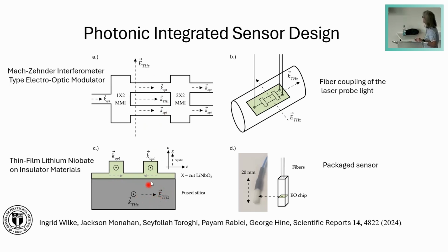These are technical details. We have X-cut lithium niobate, and the polarization of the optical mode is parallel here to the extraordinary axis of the material. Then we see here how we operate it. This is again a top view schematic of the chip. The laser light is coupled from the fibers to the device using grating couplers. And here the cylinder indicates the terahertz radiation beam. If the terahertz radiation travels in this direction, then the electric field is parallel to the arms.